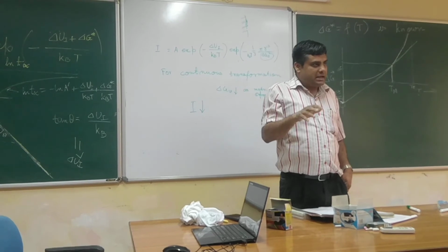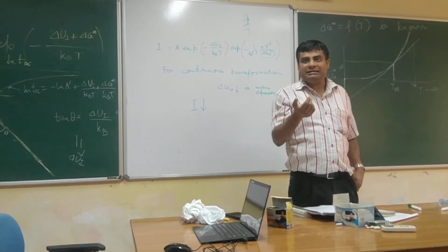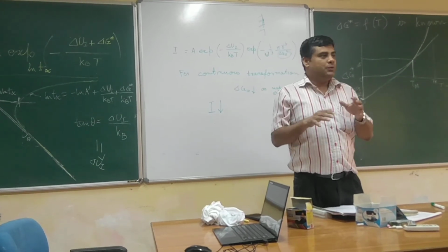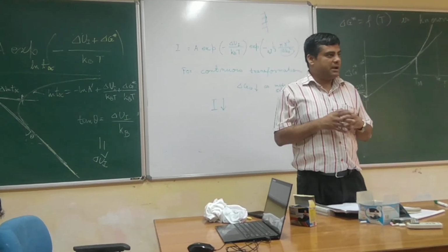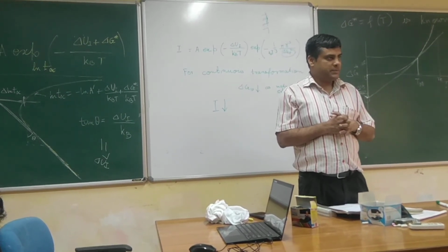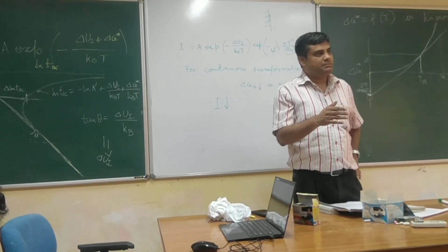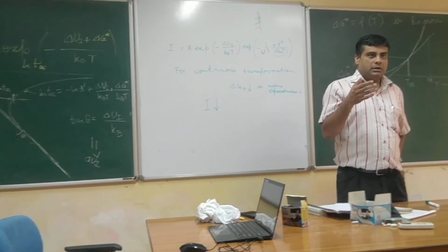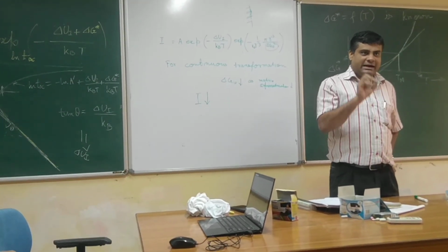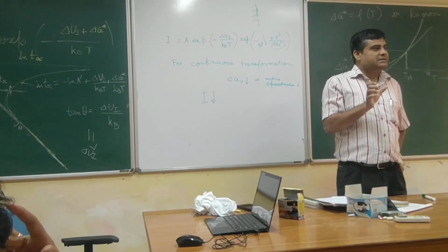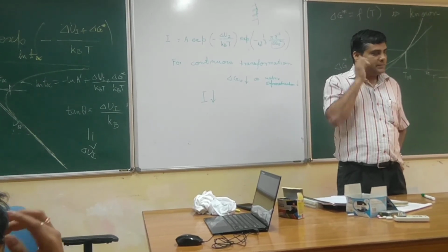It has to rearrange, some time is required for the lower temperature new equilibrium distribution of the embryos. That is the incubation time, and after that time, the nucleation rate increases to the steady state value. So this total time is the incubation time.